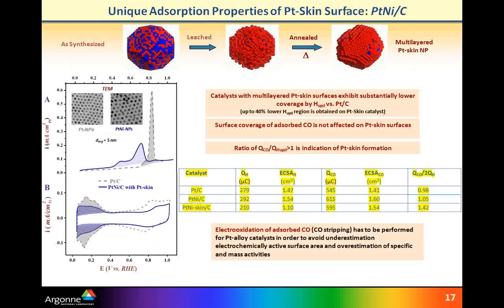So not only was the hydrogen UPD region changed compared to the corresponding platinum-carbon catalysts with the same loading, but we could also see exactly the same behavior as Nenad mentioned from the single crystals, where unique adsorption properties appeared in terms of a substantial difference between hydrogen UPD and CO stripping charge. And therefore, that was another confirmation that we were indeed able to produce platinum skin nanoparticles with multi-layered platinum skin.